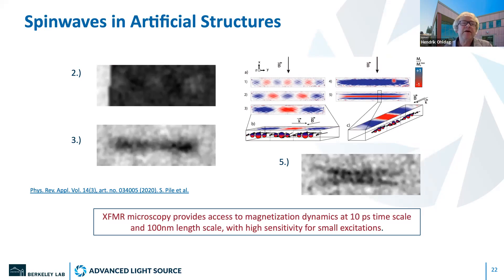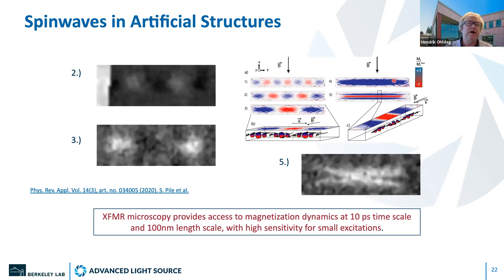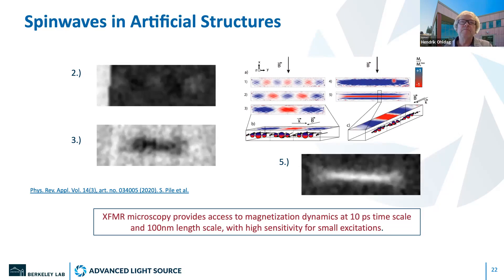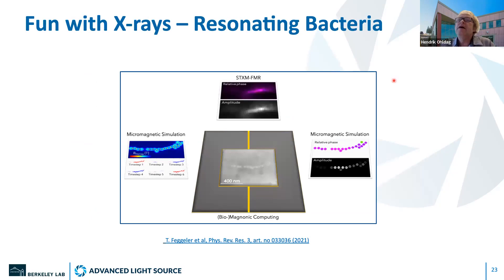We can see these modes very nicely with our technique. That means we can resolve magnetization dynamics on the 10-picosecond timescale, which is very encouraging because that's the relevant timescale for technology. Also, the upper end of our time resolution extends to microseconds, so we can cover a very large range of timescales. Our next step was going away from these artificial structures to structures made by bacteria. This is an area that is very active — the idea is that magnetotactic bacteria can actually produce little chains of magnetic nanoparticles with very high accuracy and very little deviation from particle to particle.